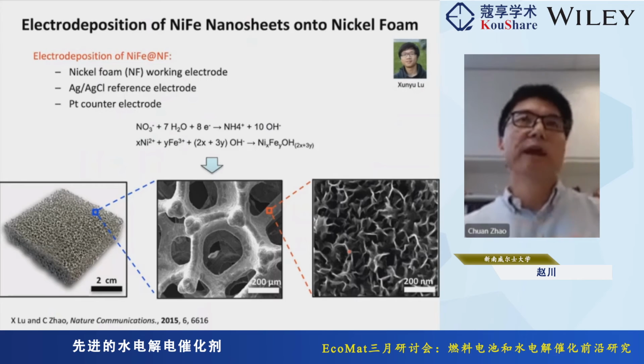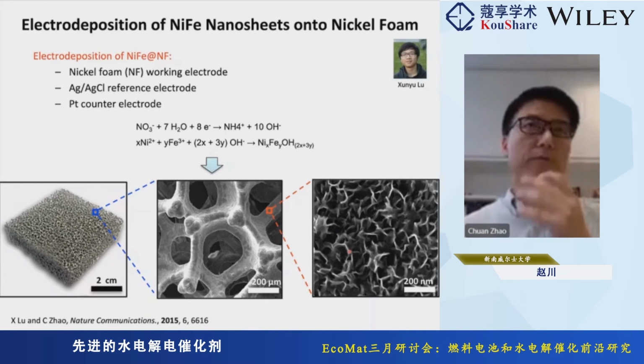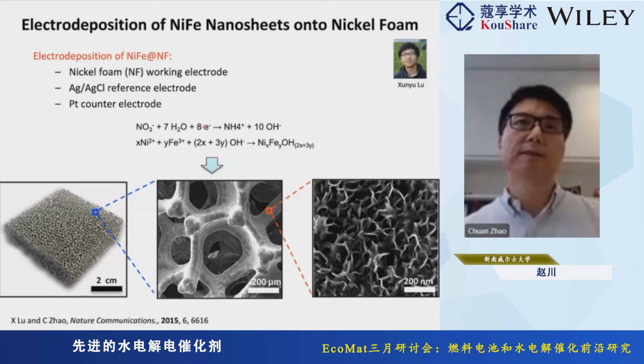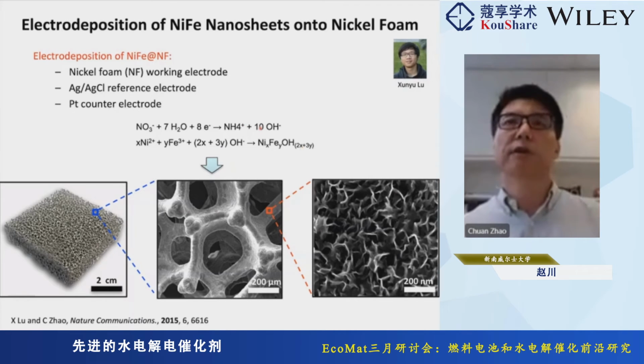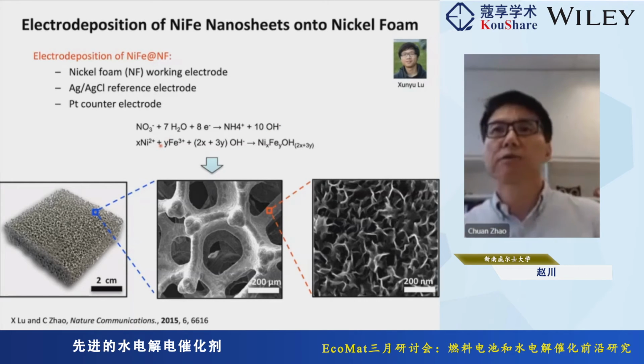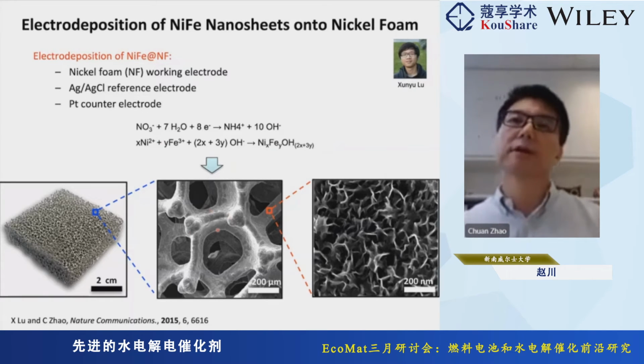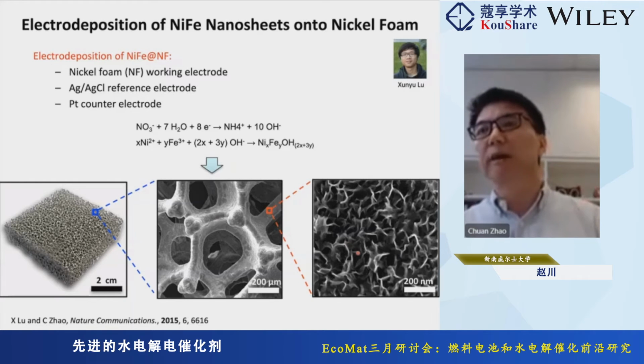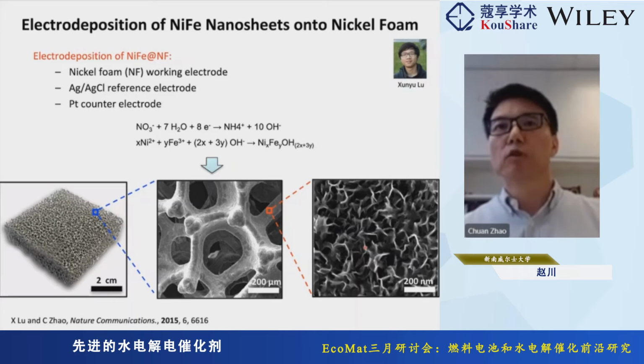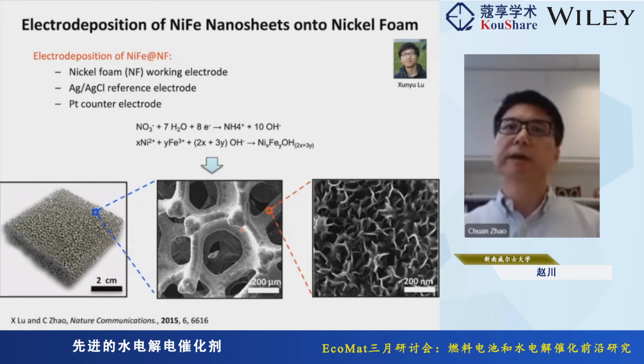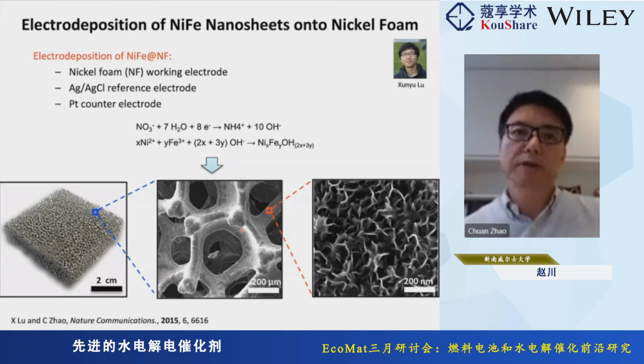Back in 2015, we introduced this work, and we used a very simple method to prepare nickel iron onto a highly porous electrode substrate, which is nickel foam. We use nickel foam as the substrate and do the electrodeposition in a nitrate-containing solution. Nitrate can be reduced to locally generate OH, hydroxide ions, which then react with nickel and iron to form a hydroxide coating onto the porous nickel foam substrate. We found that extremely thin nanosheets of nickel iron formed on the nickel foam substrate.